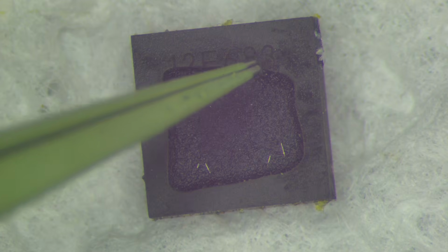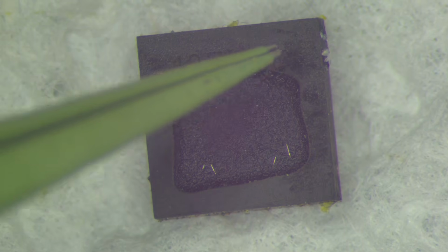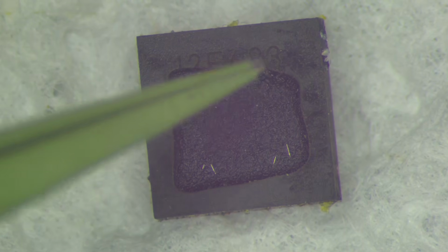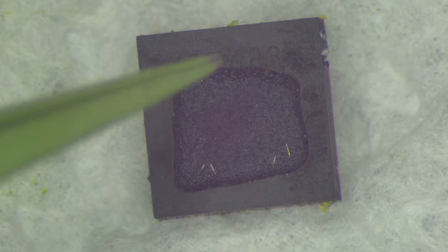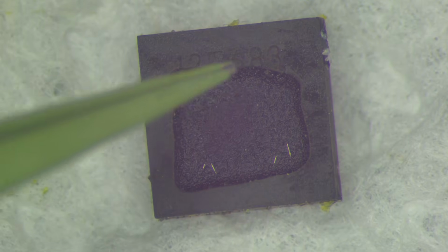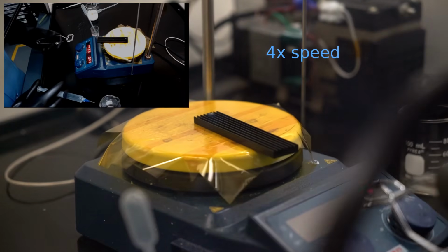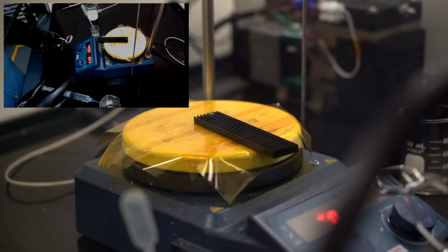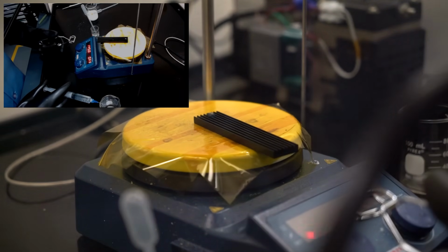If you don't have an x-ray of the package, figuring out exactly how big of an aperture to leave and where to place it can be a little bit of an art form. So in this case, I apparently cut the corner just a little bit too close. So I've reapplied the mask off camera, leaving a bigger aperture above the sample in order to hopefully etch out that corner a little bit more.